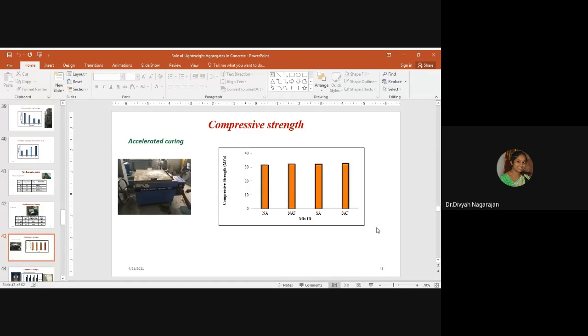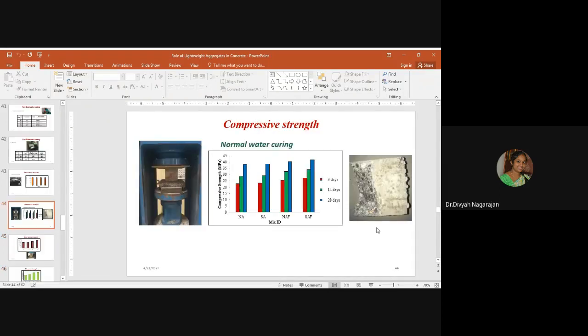It is not the exact compressive strength that will be attained at 28 days of age, but it somehow predicts the nearby compressive strength of the concrete. It can be seen from the graph that the compressive strength predicted through accelerated curing is all above 30 MPa for all types of concrete. Coming to compressive strength using normal water curing, the 3, 14, and 28 days compressive strength was found out.